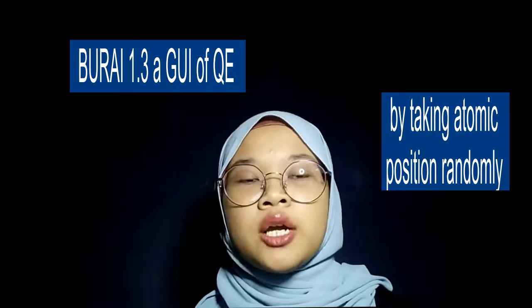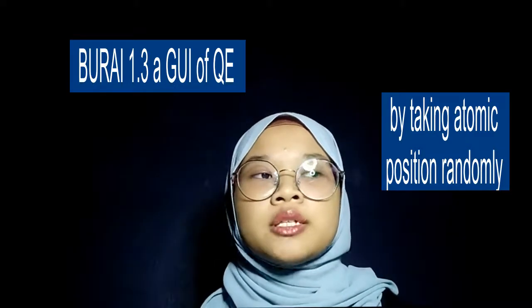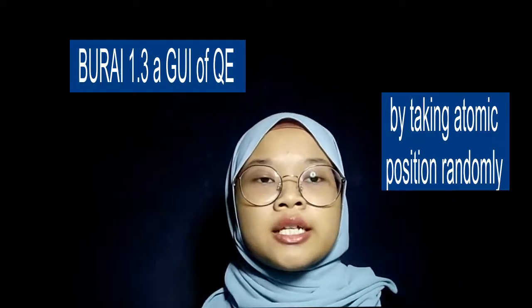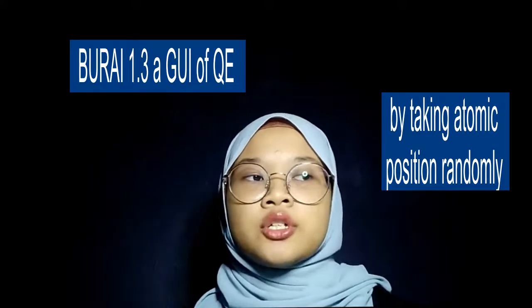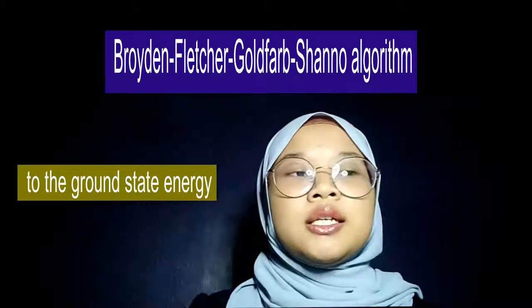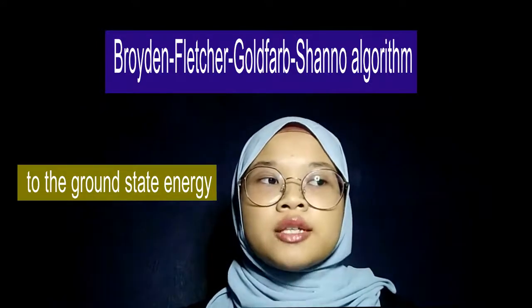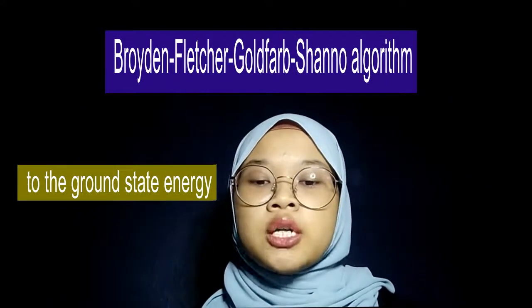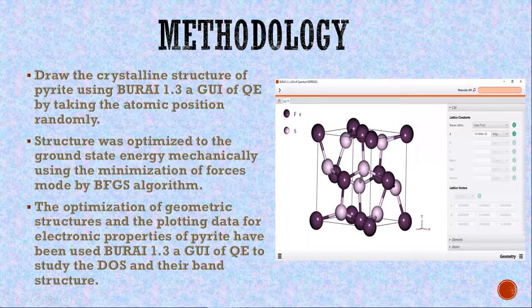So, for the methodology of this project, we start by drawing the crystalline structure of pyrite using Burai 1.3, a GUI of Quantum ESPRESSO, by taking the atomic positions randomly. Then, the structure was optimized to the ground state energy mechanically using the minimization of forces mode by BFGS, which is the Broyden-Fletcher-Goldfarb-Shanno algorithm. Then, for the optimization of geometric structures and plotting data for electronic properties of pyrite, Burai 1.3 was used to study the density of states and band structure.